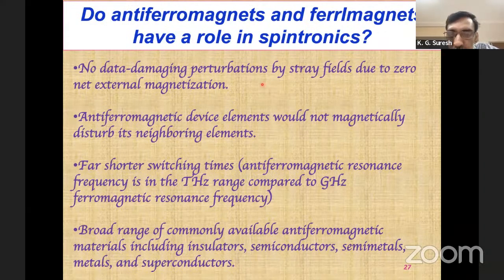It will be ideal. Of course, you need to have a magnetic order, so the only way is to have an antiferromagnetic order. That is the reason. Also, the switching speeds are much larger because the antiferromagnetic resonance frequency is larger, and therefore the time scale will be less. So it actually is a faster method, or it will result in faster devices. Of course, I told you that I'm not at all a device person. So that is the reason why it has become very important from the actual device point of view. Antiferromagnetic materials are more sought after these days than the ferromagnetic ones.